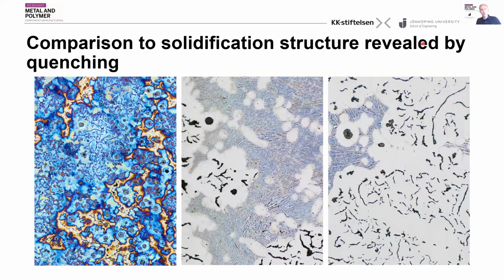Another thing to note is what these patterns that you see represent. So you can actually see some strange features. You have blue around the nodules, blue in the eutectic cells, and some blue in some kind of branch-like structures. And if we look at the material when we have treated it in a different way, in the center here,